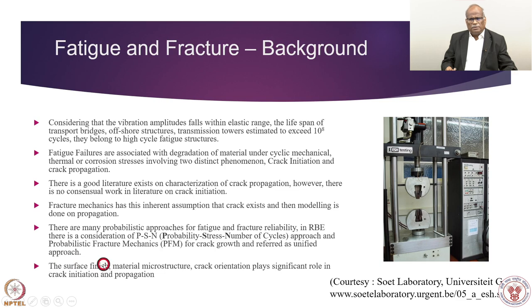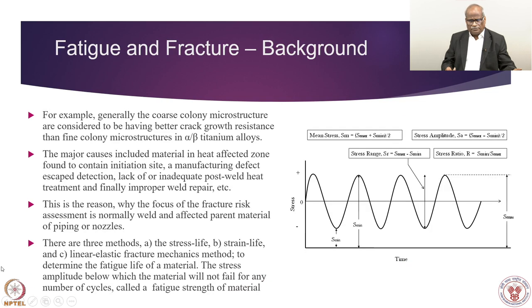There are many parameters that govern crack propagation or even crack initiation. If the surface finish is not good, then there could be some initiation. Material microstructure and crack orientation play a significant role in crack initiation and crack propagation.